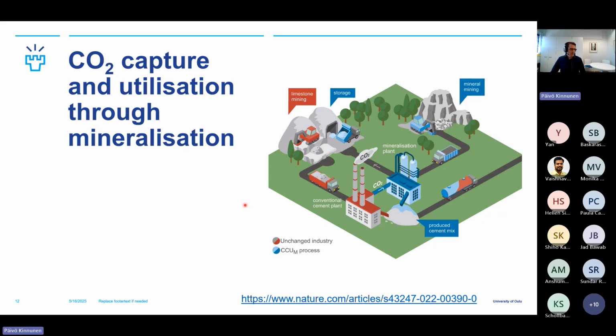So here's one proposed way of utilizing these mineralization wastes, and this is from the literature. You have your mining of limestone, so this is your calcite or your OPC feedstock. You're mining that, and then you're using a conventional cement plant. And then what is envisaged here is that you mine magnesium silicate, and then you get the CO2 from the cement plant to mineralize that, and then store that magnesium carbonate in another mine.